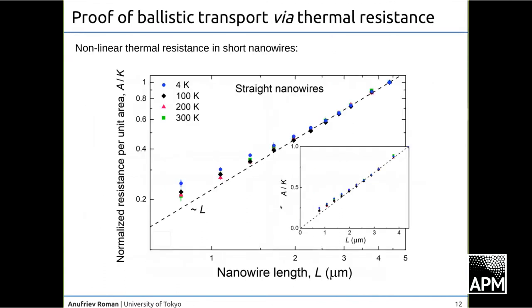literature. We can replot this data in terms of thermal resistance, because it's very important to demonstrate that it's not due to contact resistance, even though it's an optical method, sometimes contact resistance might be the problem. We can see basically the same thing: long nanowires follow the trend of resistance proportional to L, which means diffusive regime, but short nanowires deviate from this linear dependence of resistance on length. And the lower the temperature, the more it deviates from this L trend, which also proves the same point, that it becomes more ballistic at low temperature.